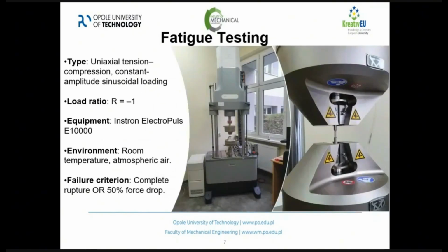So after the initial tensile test, we did some fatigue tests. They were all uniaxial tension-compression with constant sinusoidal amplitude, load ratio -1, at room temperature. And there was also a failure criterion. It was either a complete rupture or a 50% force drop or displacement amplitude drop in this case.